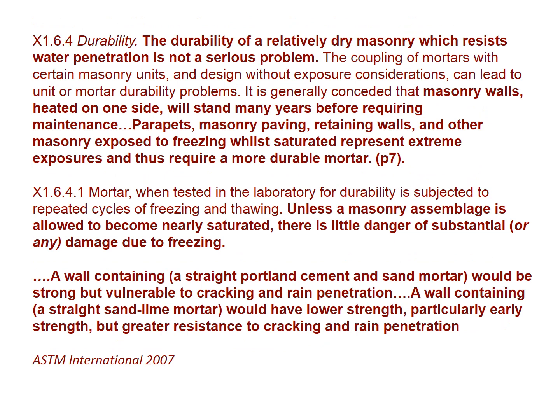And again, the ASTM's guidance from 2007 understands this. The durability of a relatively dry masonry which resists water penetration is not a serious problem. The coupling of mortars with certain masonry units and design without exposure considerations can lead to unit or mortar durability problems. It is generally conceded that masonry walls heated on one side and with wind on the outside will stand many years before requiring maintenance. Parapets, masonry paving, retaining walls, and other masonry exposed to freezing while saturated represent extreme exposures and thus require a more durable mortar. But these are small elements of a building overall. The rest of the building requires a mortar that will get rid of received moisture by capillary action.